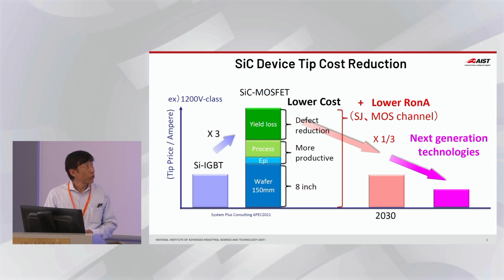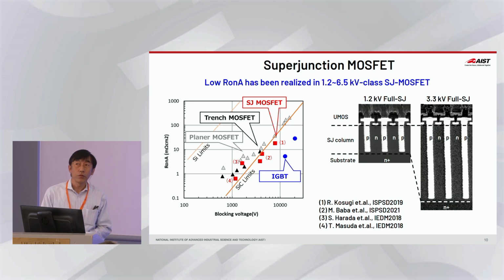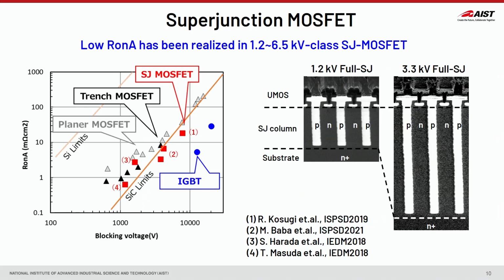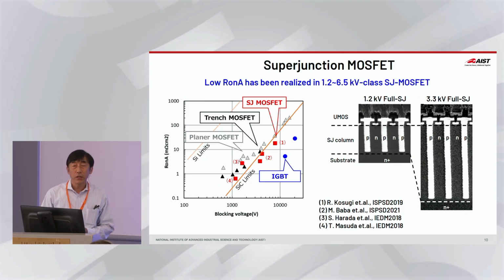About the SJ technology, we have realized some good results. Low on resistance has been realized in the 1.2 to 6.5 kilovolt classes. You can see the red plots in these figures have already exceeded the unipolar limit of silicon carbide. So we think the superjunction is a big advantage for silicon carbide over the other wide-bandgap materials because it is difficult to control the p-type doping concentration in other materials.